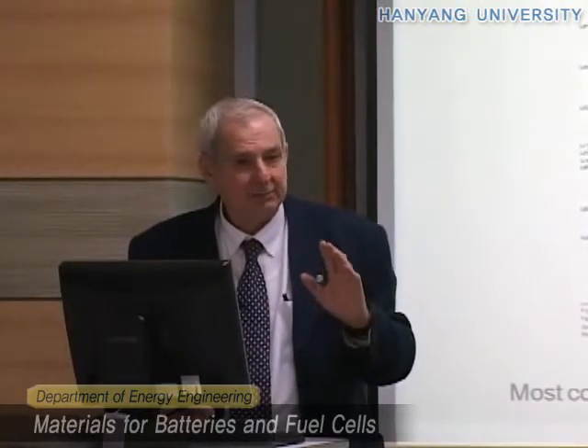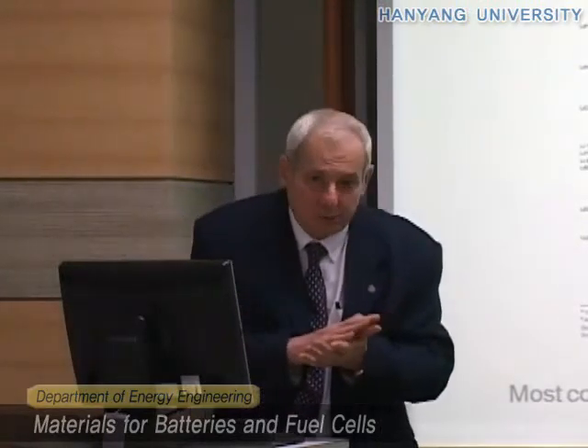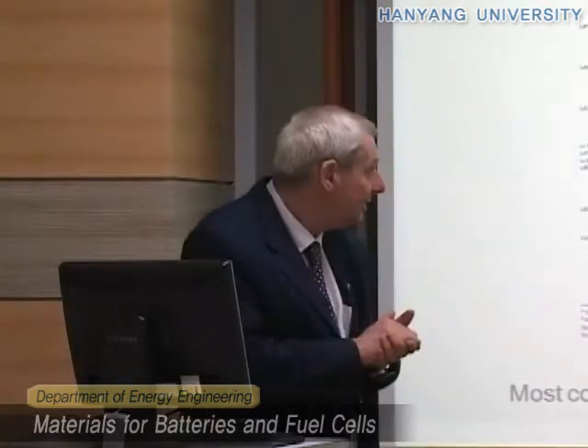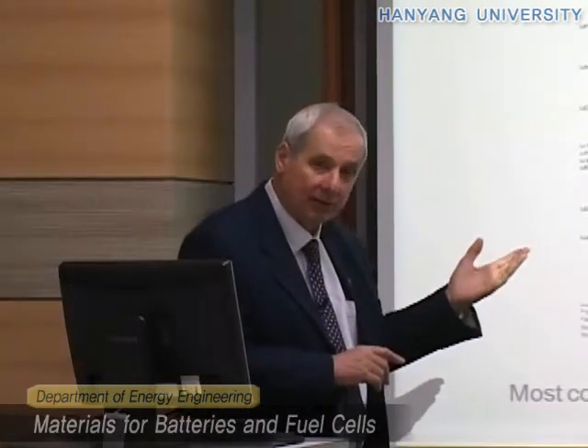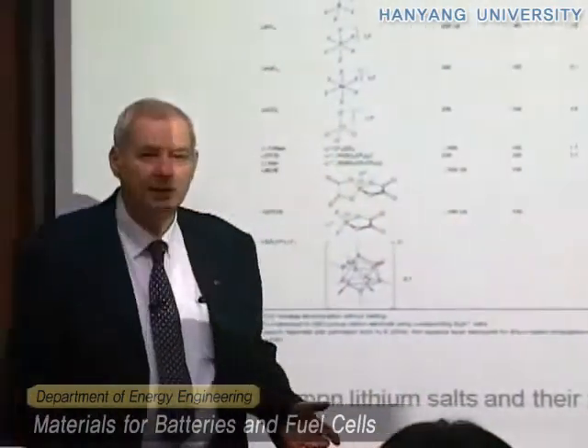And this salt corrodes aluminum. This is the reason why the stability is very low. So never use this salt for a lithium battery, because a lithium battery usually has a voltage higher than 3.5, whatever. And so you will corrode the aluminum substrate.